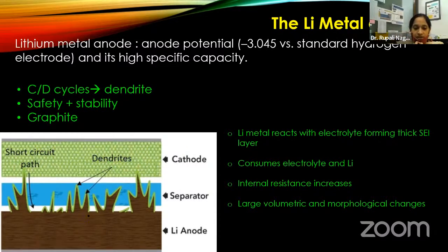You can see that initially, let's say if this was lithium metal foil, then now it has protruded out. So volumetric changes have taken place, and these are unstoppable. And then the morphology has also changed now. So now these sharp ends or these sharp sides, these pockets, will become regions where more reactions will take place. Therefore, these are unwanted, but we do not have control over it.